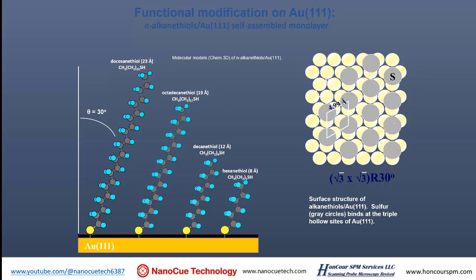Then you have basically covered up all the gold, and you look at the terminal functional groups. The only thing exposed to the interface are the terminal functional groups, in this case, CH3. So if you form a self-assembled monolayer on the surface of gold, the surface is very hydrophobic and very, very clean, CH3.